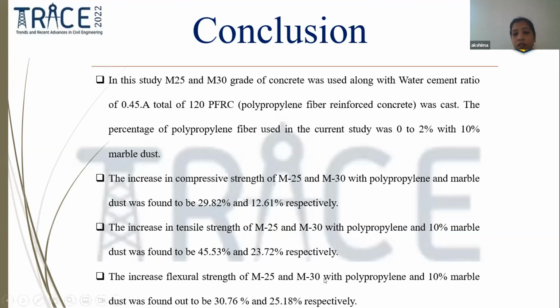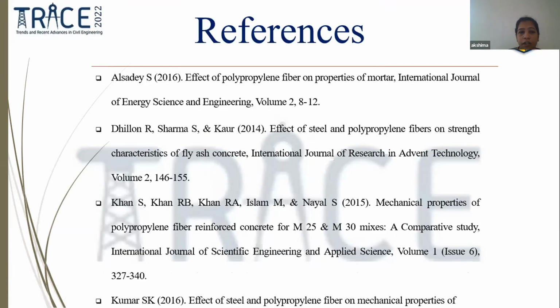The increase in compressive strength was found to be 29.82 for M25 and 12.61 for M30. Next, the increase in tensile strength when comparing both mixes came to be 45.53 for M25 plus 10% marble dust and 23.72 for M30. The increase in flexural strength came to be 30.76 for M25 and 25.18 for M30.